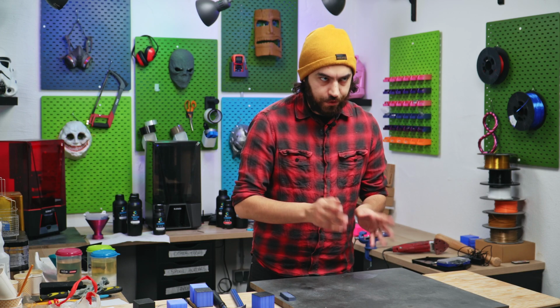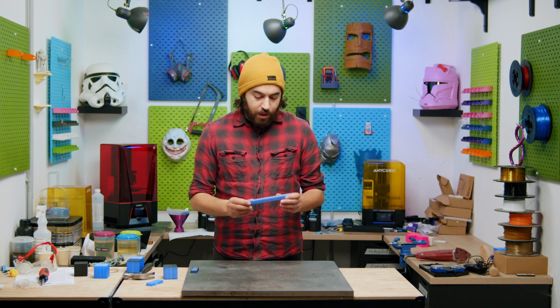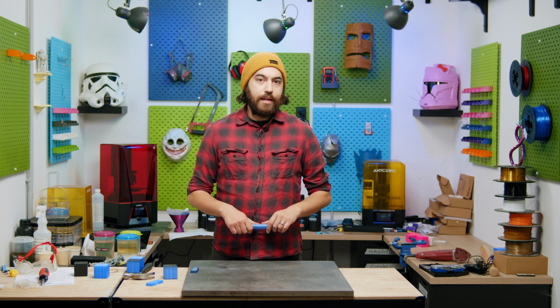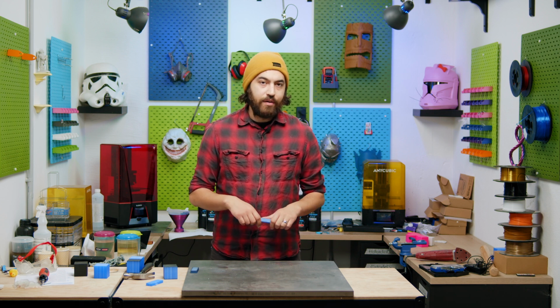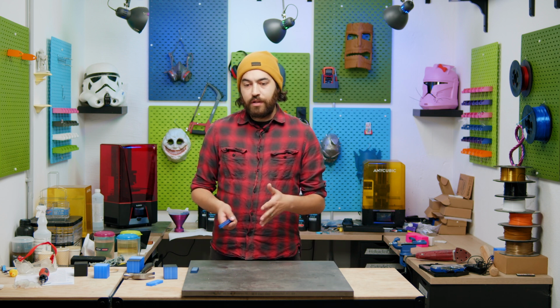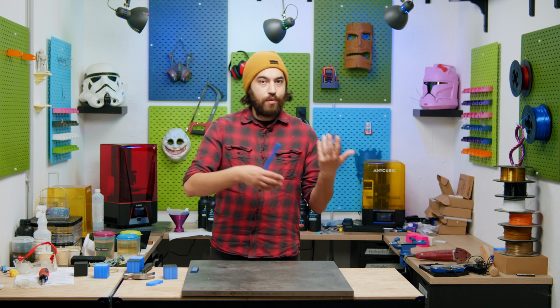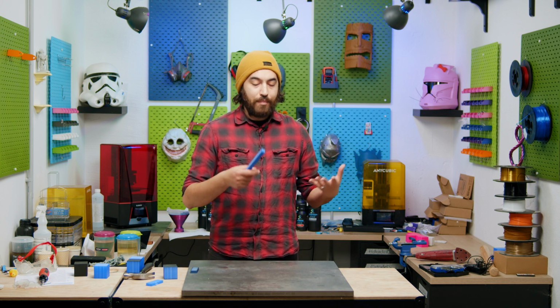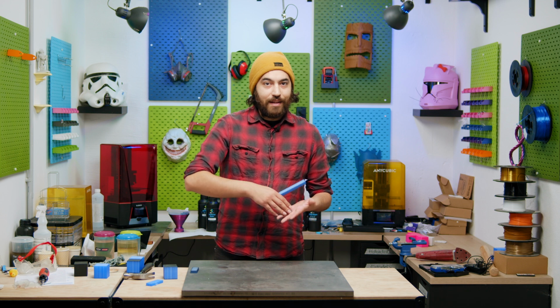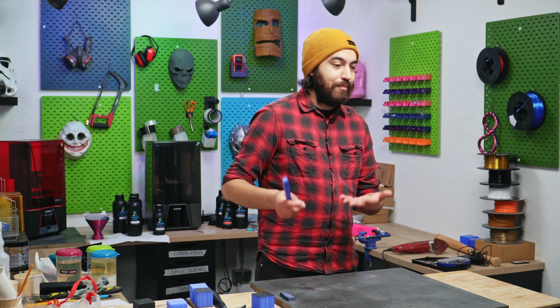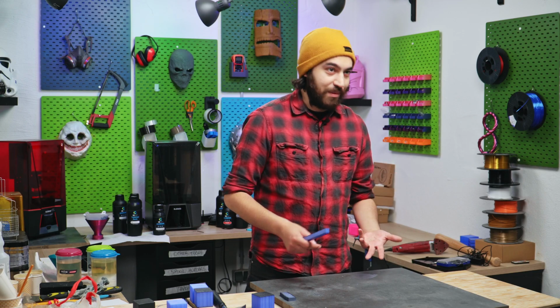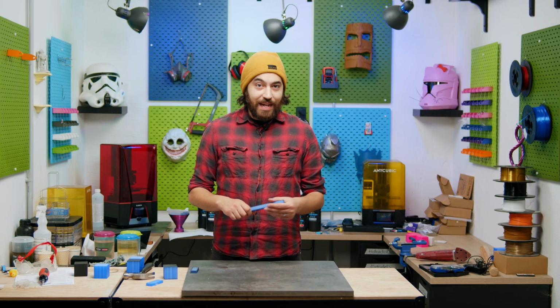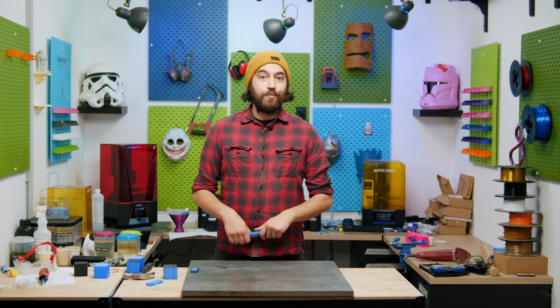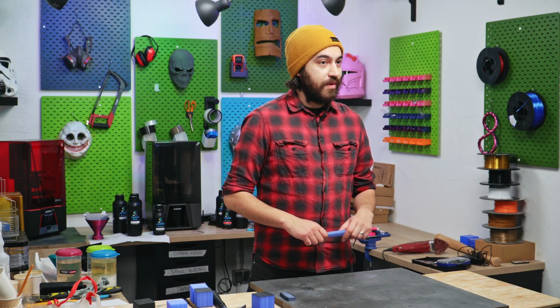Okay, so we did have some issues when we were trying to get this working, and there are drawbacks too. Even with PETG and TPU being super sticky, we did have issues with layer adhesion. So we chose an infill pattern that had overlaps. Initially, we wanted to use a concentric pattern, but these are not overlapping the perimeters or themselves. They're just vertical pillars that go up and they're not connected to anything. Because of that, the nozzle had to jump a gap and then start printing, and because of that, the layer adhesion was abysmal. We also tried this with carbon fiber PETG, and again, layer adhesion just wasn't good. We couldn't get reliable results from that at all.